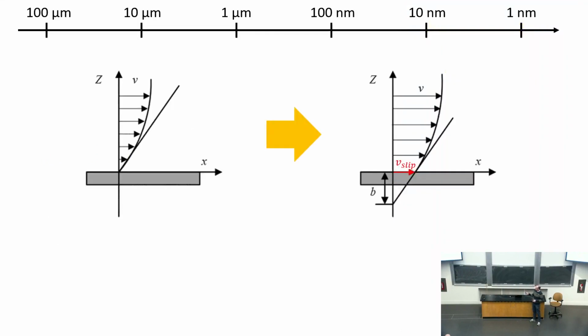As an introduction, very often in large-scale systems, when you look at hydrodynamics textbooks and at a flow profile at the boundary to a wall, you will see that the flow velocity goes to zero at the wall. It's called the no-slip boundary condition, and there have been tons of experiments showing that this applies in pretty much all systems. But if you go to very small scales, in experiments we do see finite slip, and it matters.